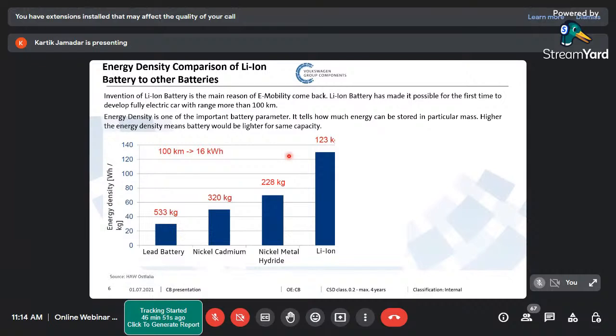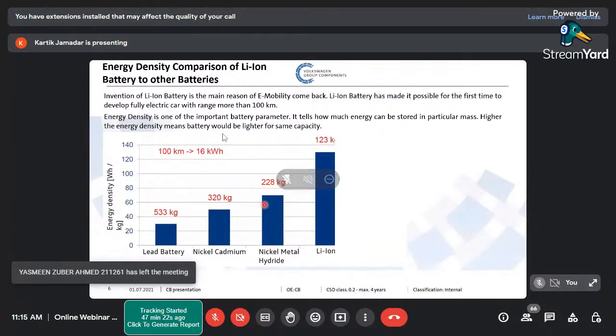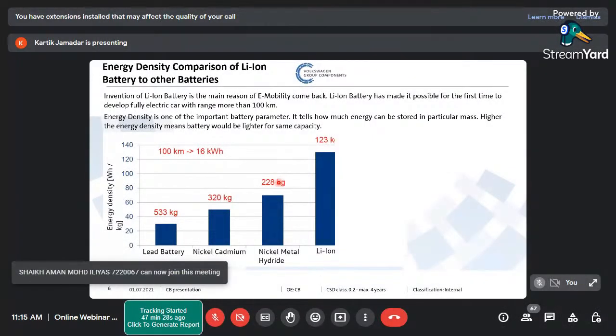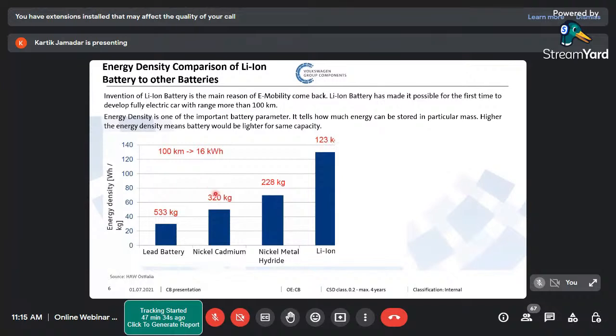You can give this energy either by an IC engine, by fossil fuel, or from the battery. The amount of energy is the same. For that 16 kilowatt hours, I would need around 533 kilograms of lead batteries. Then came the secondary battery called nickel cadmium, which is nowadays more or less prohibited because of the toxicity of cadmium. We needed 320 kilograms. So on the energy density side, it was better. When we went to nickel metal hydride batteries, we needed only 228 kilograms. Now came the next generation, lithium ion technology. We need only 123 kilograms. It means one fourth of the battery.